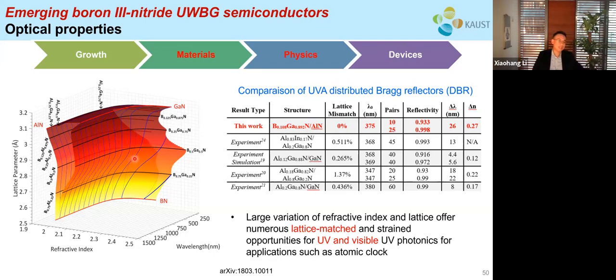materials. And this lattice matching is very important for devices, because if you have lattice mismatch, such as the studies shown here, your device may accumulate a large degree of strain, which may crack your sample surface and render your device not useful, right? So based on this, we can then construct the superlattice without the lattice mismatch. Then we can grow a very thick superlattice without worrying about the strain accumulated in the device structure.